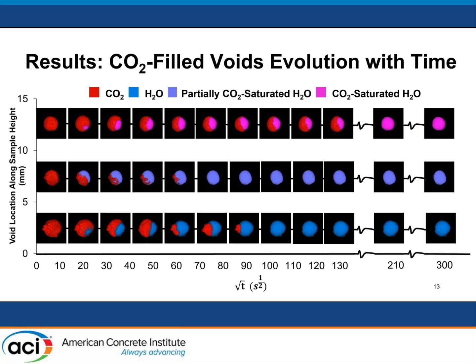If you remember from the CT scan slices, a gas will show up as a darker black color, whereas water shows up as a lighter color. And what we observed was that as the water became CO2 saturated, the attenuation was actually changing with time. That was an observation that was made, and that's just what's being shown here: water compared to CO2 saturated water had a slightly different attenuation coefficient.